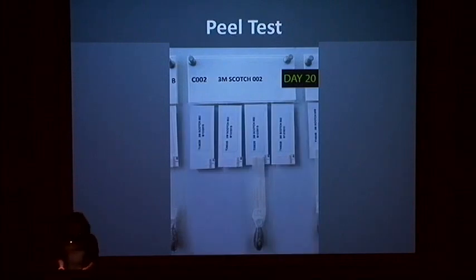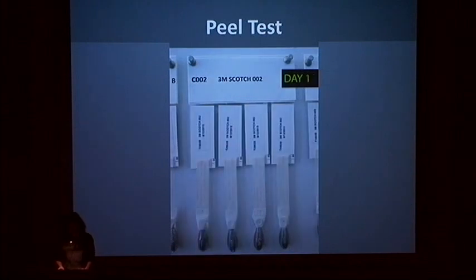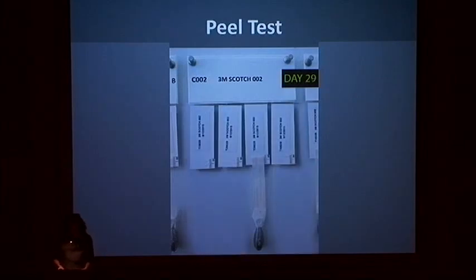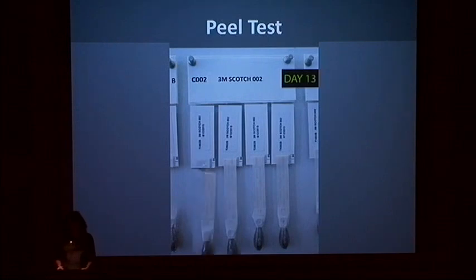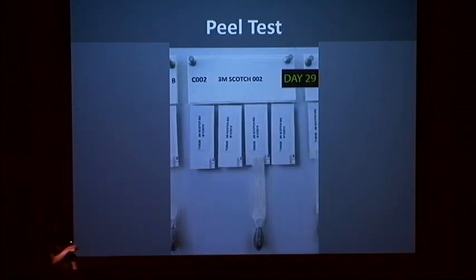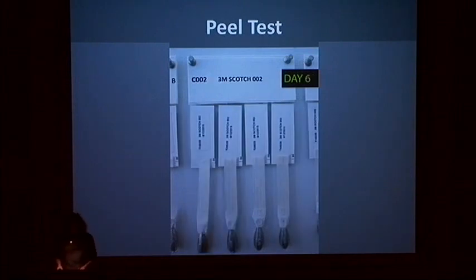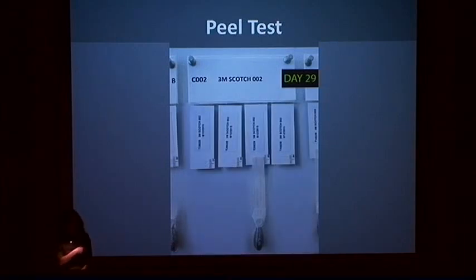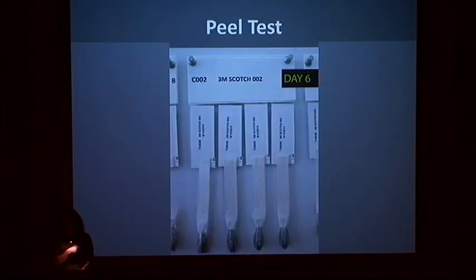Okay, it works. In the peel test, however, there was much more action. We documented the cards at all stages. The scale bar on each sample allows us to monitor and quantify the creep. And this is the little scale that we apply to each sample, so we can track how each sample creeps during this test.